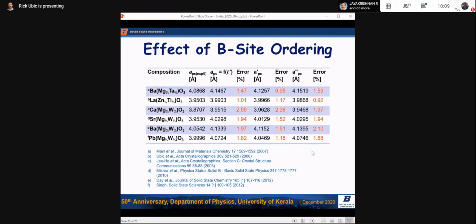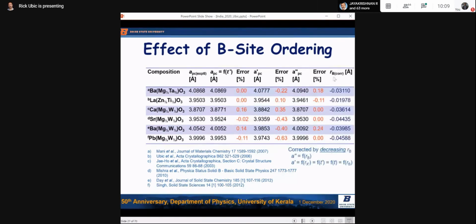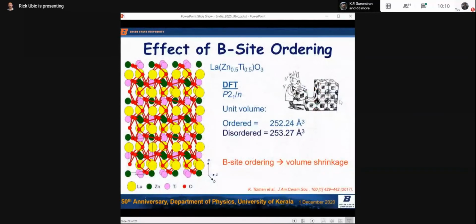So what's going on? It turns out if we correct the B-site size in this case, we can essentially eliminate those errors. Now they're a mixture of positive and negative. They've basically been eliminated, and all of these corrections are negative. So we've shrunk the B-site size. What that means is when things order on the B-site, they shrink. And you'd expect this. Ordered things pack more efficiently, so you'd expect them to shrink upon ordering. And that makes sense. It explains a lot of things in material science.